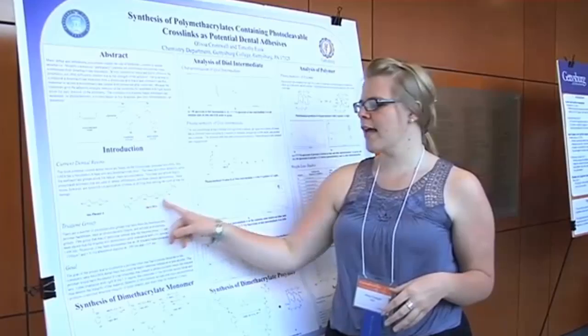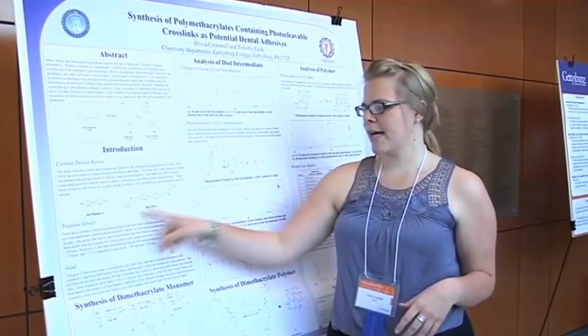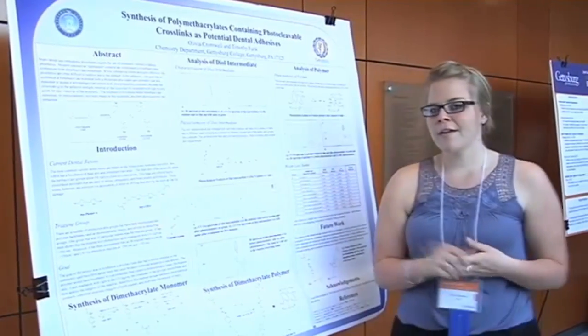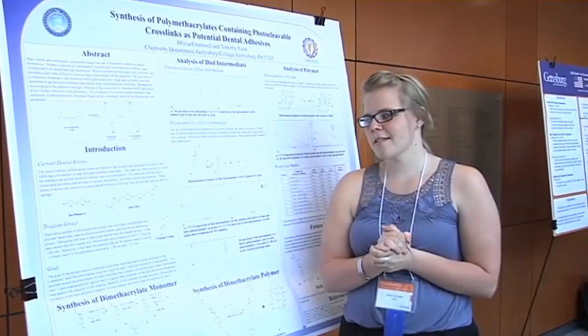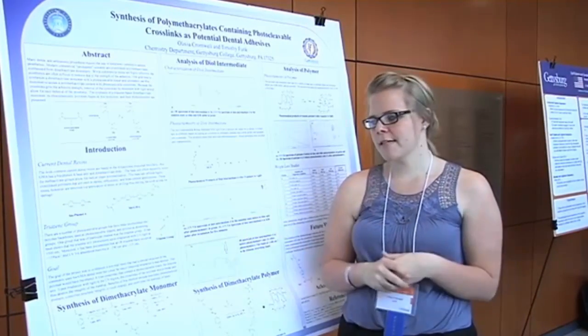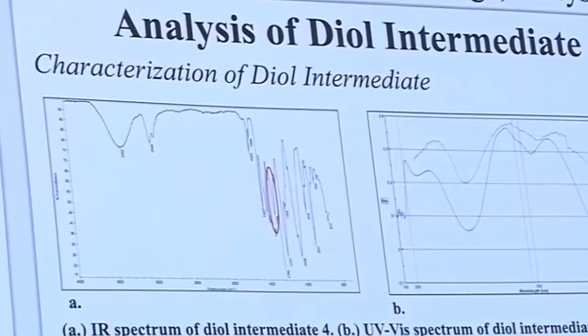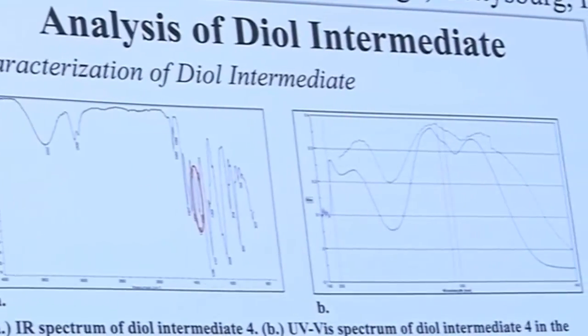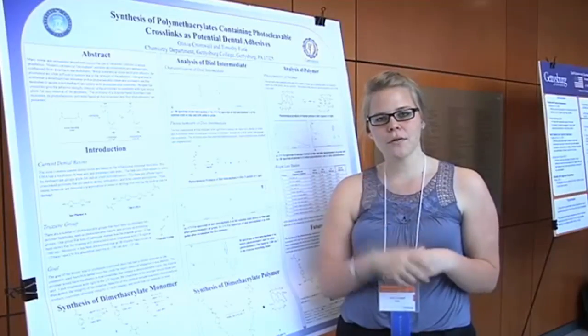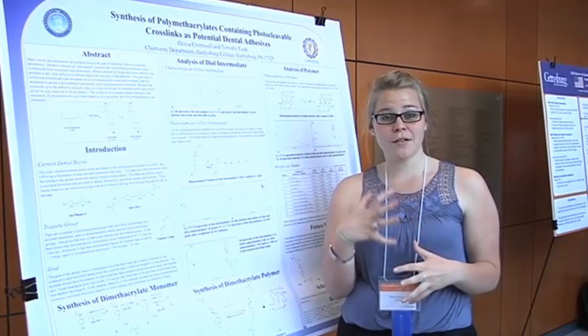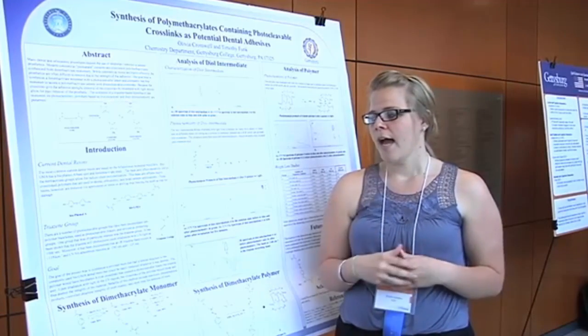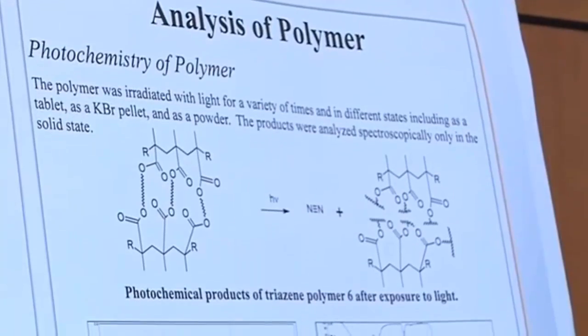Current dental resins are based on this molecule here called bis-GMA, and it's a bifunctional monomer containing a bisphenol A central group and dimethacrylate ends. It undergoes radical chain polymerization to yield the bis-GMA resin. It's applied to the tooth via an acid etching method. So acid is applied to the tooth, leaving a porous material behind on the tooth. And then the resin is applied and then cured with light.